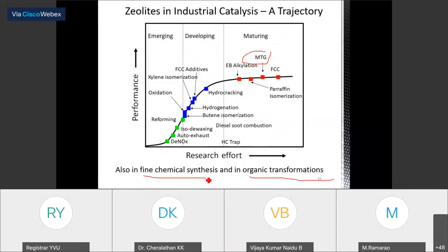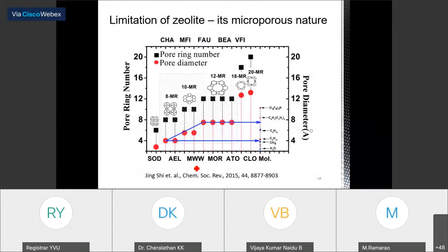So it's no wonder that zeolite is a wonderful catalyst, but it has some limitations. Because if you look at the zeolite structure, they are essentially micropores. So the pore size is below 2 nanometers. So you cannot use zeolites to process molecules which are larger than 2 nanometers. That is one of the limitations of zeolites.